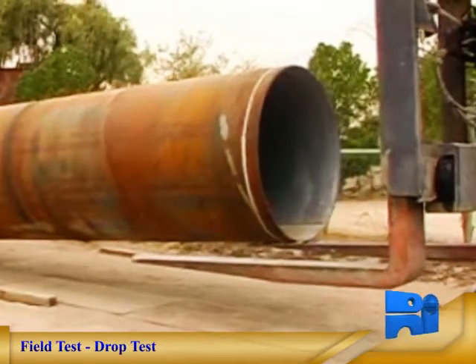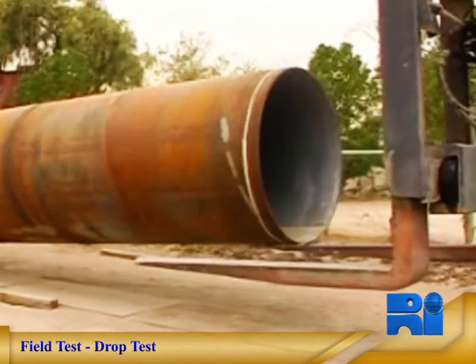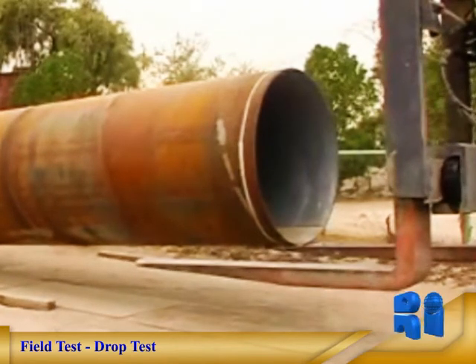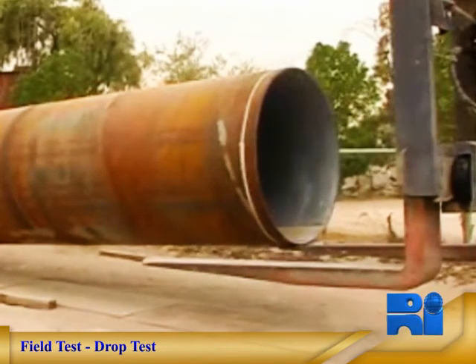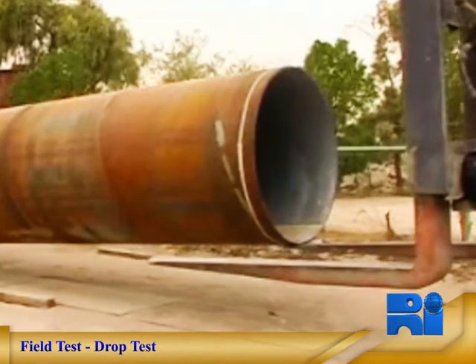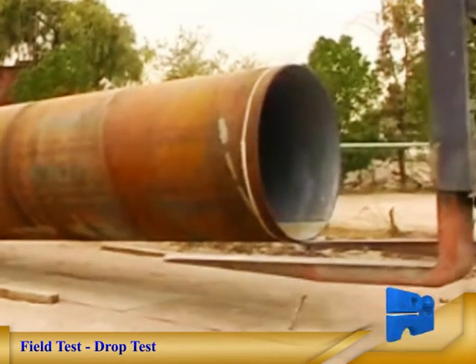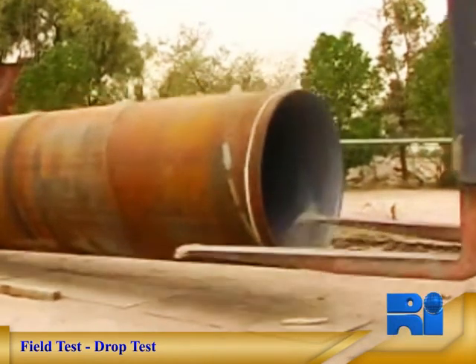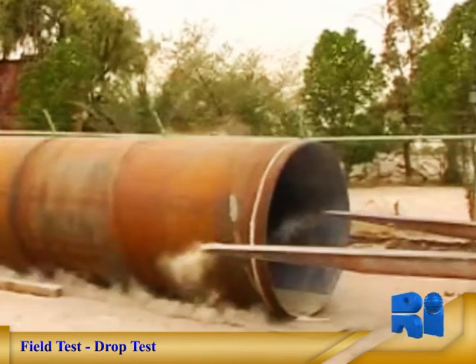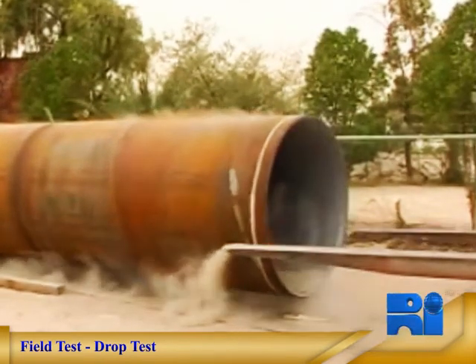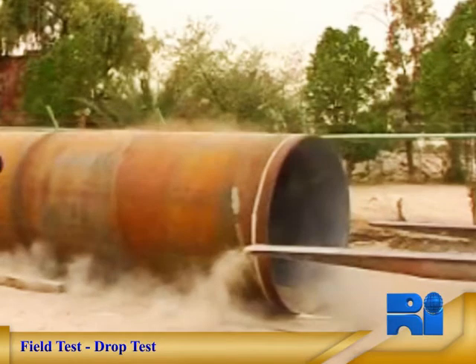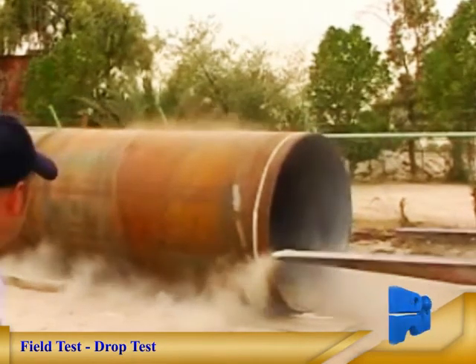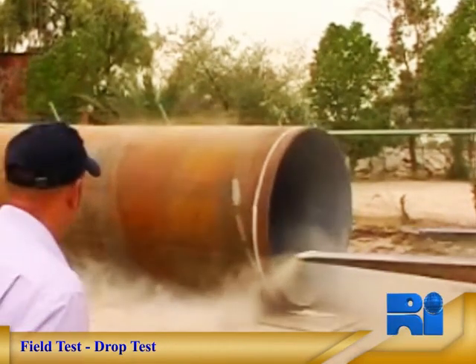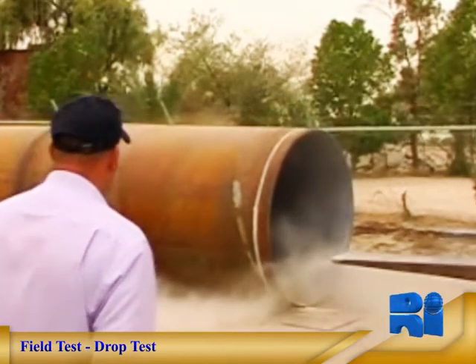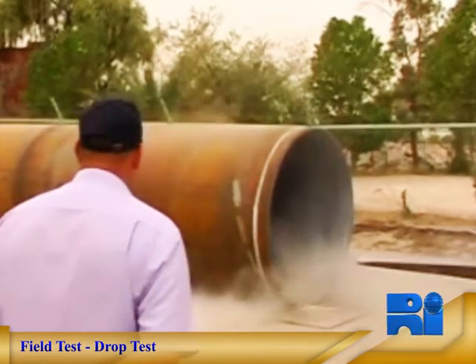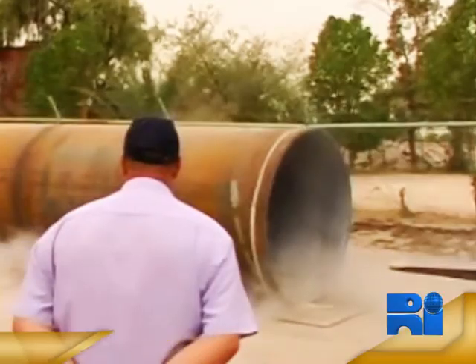In order to demonstrate the strength and robust characteristics of Raymond's Centriline process mortar lining, pipes are sometimes subjected to extreme testing. In this test, an 1800 millimeter diameter steel pipe with a 12 millimeter thick cement mortar lining is dropped from a height of 1 meter in slow motion. You can see the tremendous stress put on the steel pipe, yet the Raymond Centriline process mortar lining remained in place and undamaged.